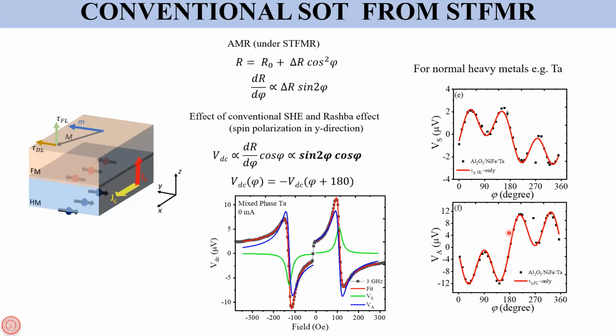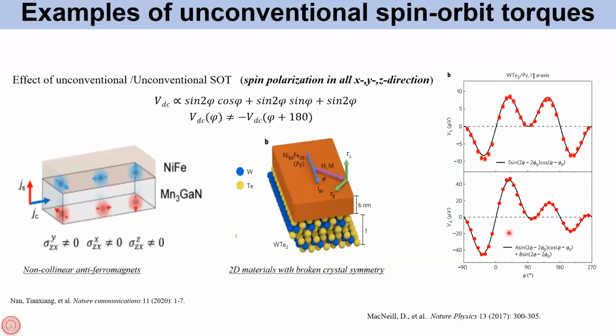So now, when you go to other materials, people have shown that beyond this conventional torque, there can be something called unconventional spin orbit torque. Here I show some examples. There have been many reports by now which show unconventional spin orbit torque. The first one here is from non-collinear antiferromagnets, where they have shown that you can get spin polarization which is out of plane as well as along the x-axis, which is along the current direction.